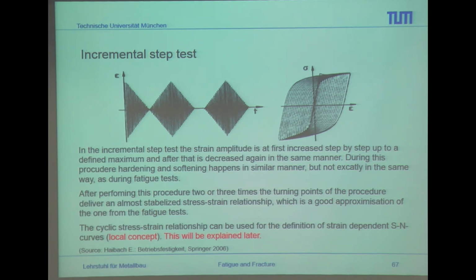If you at the end separate on the applying of the loads, on the testing procedure, you can talk about 9 different incremental step tests you can conduct on your material. But how is it going to be done? Usually the incremental step test is defined by cyclic loading, which looks like a triangle or a rectangle. You start at first with the plastic deformation in the tension test, and afterwards you decrease your loading and increase your loading again, and so on. And due to this, you get a shape of the hysteresis, which looks for the whole testing like this.